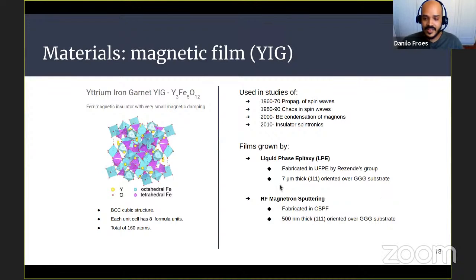So the damping is very different. Here from LPE, they are in the order of 10 to the minus 4, and from magnetron sputtering, they're in the order of 10 to the minus 3, the alpha, the Gilbert damping. So very different magnetic properties. Okay, so we used these two. I'm going to say in the results when I used one or the other. The main one was the LPE one, but we did some testing with the magnetron sputtering. And here I'd like to thank Rodrigo Torrão for helping me with the sputtering of the YIG samples.